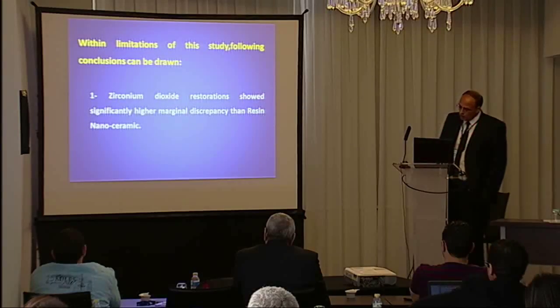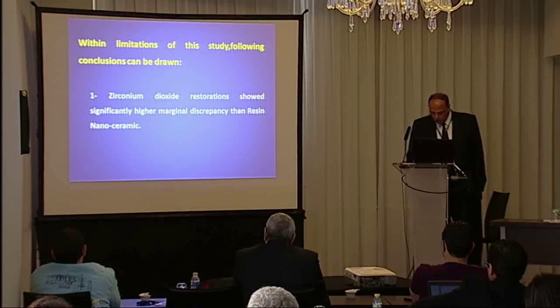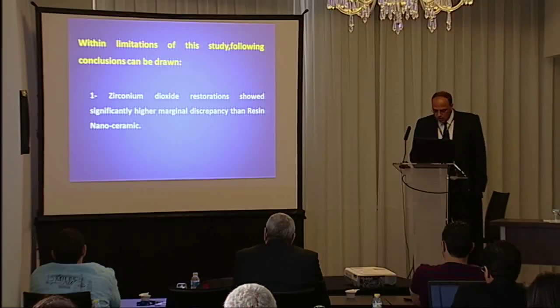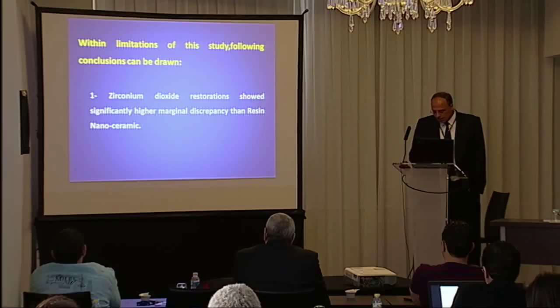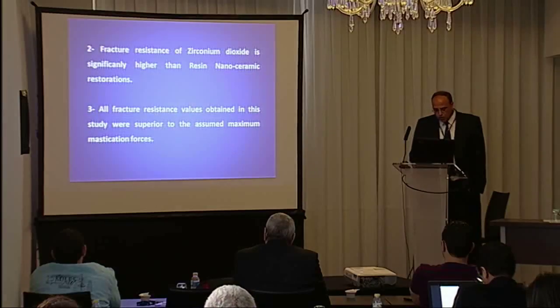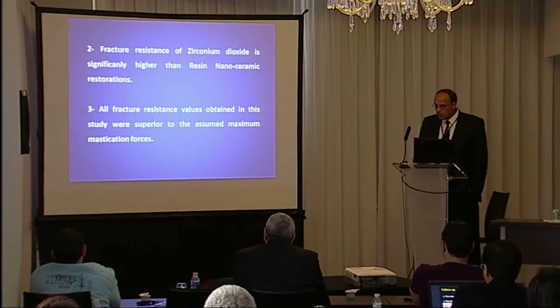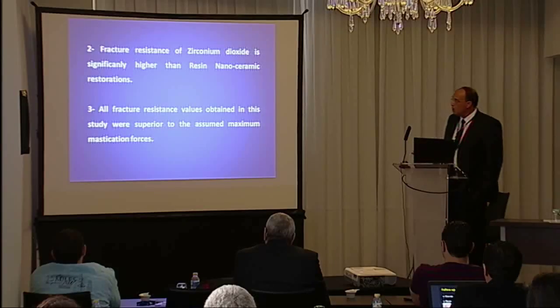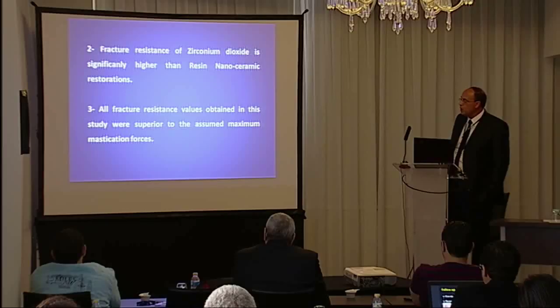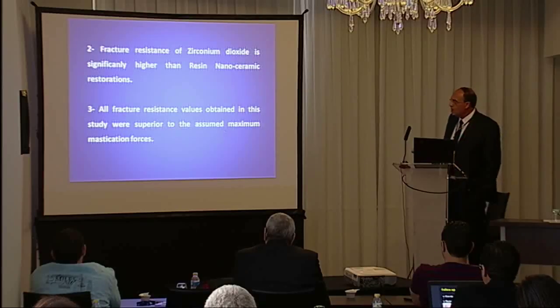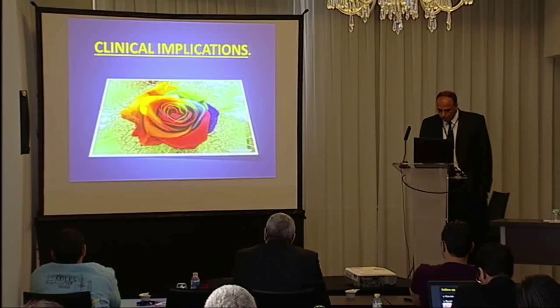Within limitations of the study, the following conclusions can be drawn. One, zirconium dioxide restoration showed higher marginal discrepancy than resin nano-ceramic. Two, fracture resistance of zirconia is significantly higher than resin nano-ceramic, and all fracture values obtained in this study were superior to the assumed maximum mastication force.